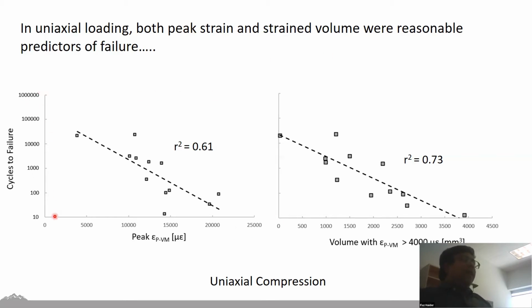On the y-axis, again, I'm plotting the cycles to failure on a logarithmic scale. On the left-hand side, the x-axis shows the peak pressure modified von Mises strain. And on the right-hand graph, it's the volume where the pressure modified von Mises strain exceeds a specific threshold. And as you can see, though the volume-based condition did work a little bit better than the peak strain, the peak condition still wasn't really bad. It still generally explained our data quite well. This is under uniaxial compression.